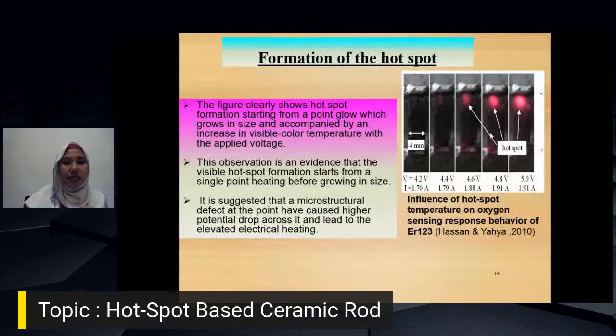Next, the previous study also showed the influence of the spot temperature on the oxygen sensing response behavior with other rare earth elements. Now we have the ER123 compound, which is a ceramic rod. The figure clearly shows the hotspot formation starting from a point glow which grows in size, accompanied by an increase in the visible color temperature with the applied voltage, so at the same time the temperature also increases. This observation is evidence that the visible hotspot formation starts from single point heating before growing in size.